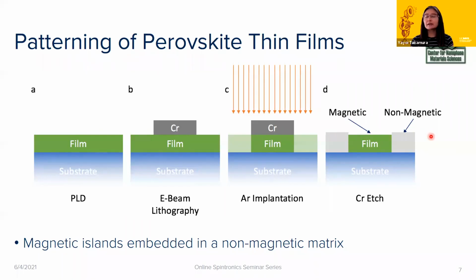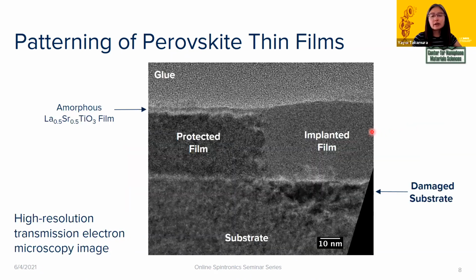So it's not actually freestanding pillars, it is an embedded nano island, and we'll find that the regions which have been implanted with argon actually swell a little bit. And so we see a small height difference between the matrix and the film. To show that in a little more detail, here is a cross-sectional transmission electron microscopy image. The implanted part of the film is on the right, the protected part is on the left. It's a little hard to see in this image, but we still do have the lattice fringes. So this is a nice crystalline region.